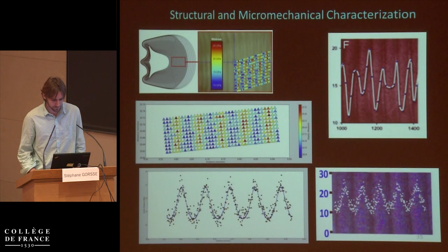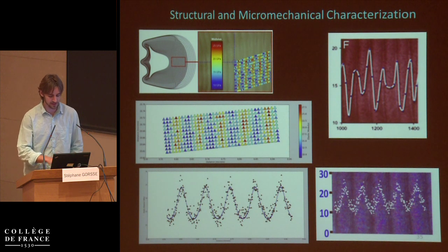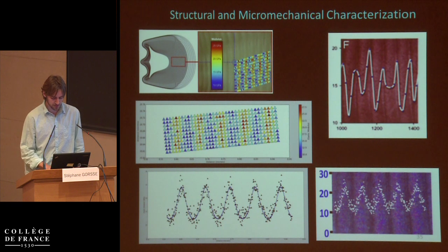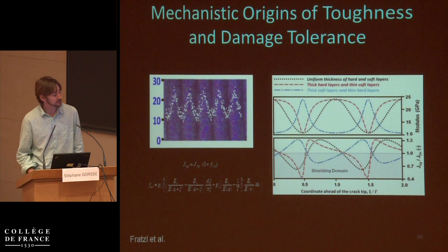So one of the things we wanted to do then was get deeper into detail and look at this periodic modulus. And so we took a mesh of points, collapsed them down, and we can see that the modulus varies between 10 and 25. So not huge, but it should be enough to create shielding domains, which could arrest fractures.